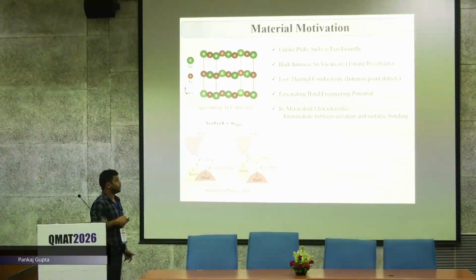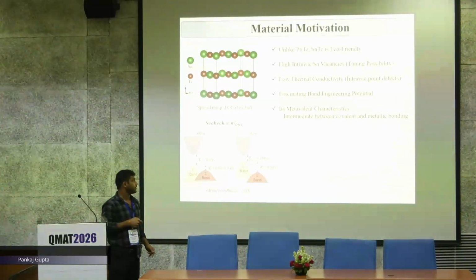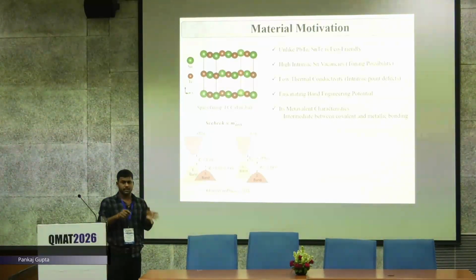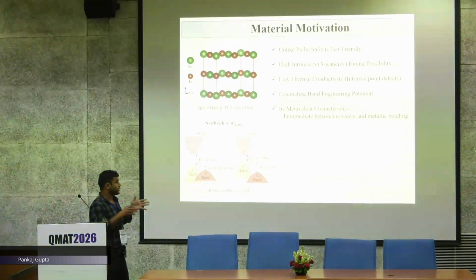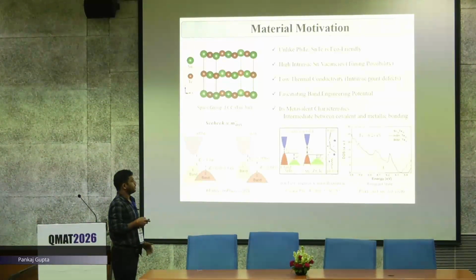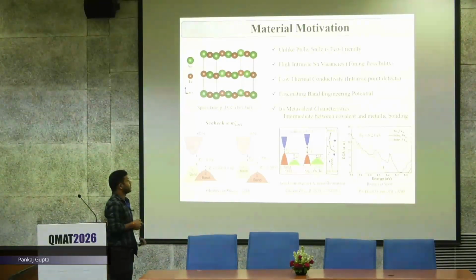Fascinating band engineering possibilities are there because by doping or alloying, you can tune this band structure. And it has metavalent characteristics, meaning it has both metallic and covalent characteristics, because SnTe has some metallic bonding character and covalent character. That is very useful from a thermoelectric point of view.